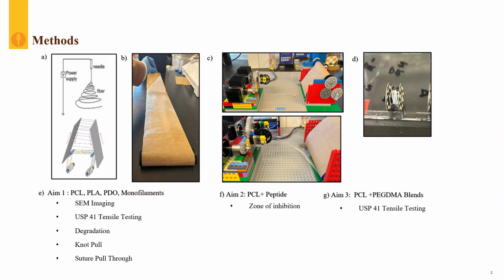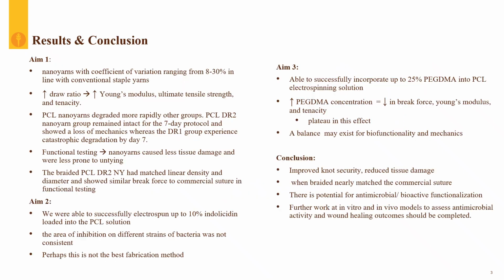For aim 1, we did testing on the PCL, PLA, commercial suture, and monofilament counterparts of PCL and PLA. We've done imaging, tensile testing according to a suture-specific protocol, degradation, knot pull, and suture pull-through. We've also done zone of inhibition for our aim 2 on the antimicrobial nanoyarns, and finally we did that tensile testing specific to sutures for the PCL and PEGDMA blends.